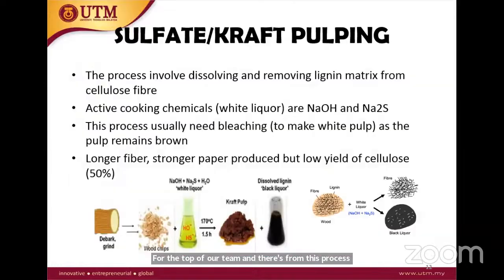Next one is the sulfate or kraft pulping. This process involves dissolving and removing the lignin matrix from the cellulose fiber, which is quite the same as the latter one. The cooking chemicals used in this process are NaOH and sodium sulfide. This process usually needs bleaching to make white pulp, as the pulp remains brown even after finishing the process. The process will produce longer fiber and stronger paper, but the yield is quite low, which is only 50%.